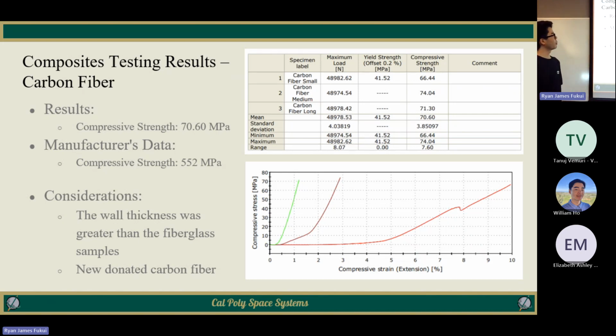So as you can see from the carbon fiber, it does not look good. The results of our compression test were 70 megapascals. The manufacturer data says the compressive strength should be 552 megapascals. That's not even a fifth, it's almost an eighth of what it should be. This is probably due to the freezer, or we just did a really bad layout.